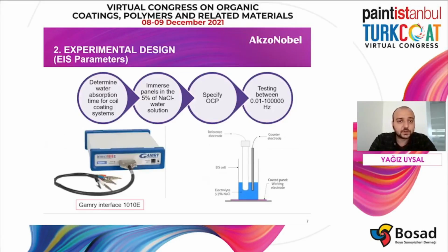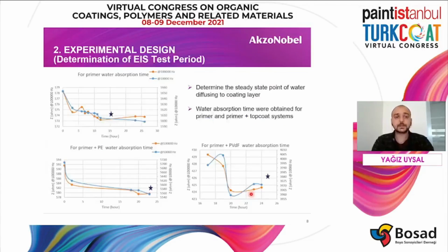And if we continue with our experimental design, we use the Gamry Interface 1010E model in our experiments, and this is our scheme for the experiments. Our sample works as a working electrode, and the sodium chloride water solution we use as electrolyte. Before starting the impedance measurements, it was needed to determine how long the panel will wait inside the sodium chloride water solution. To do so, we tested primer and polyester, and primer and PVDF samples for different durations. It was decided to immerse the panels inside the solution for 24 hours.